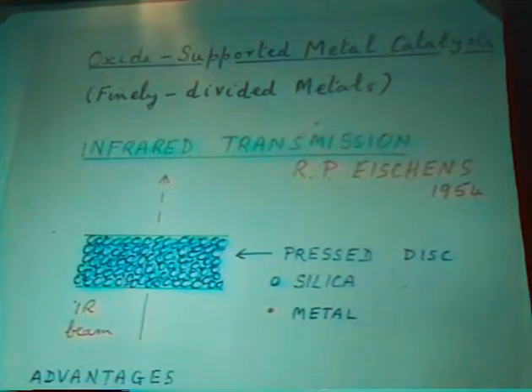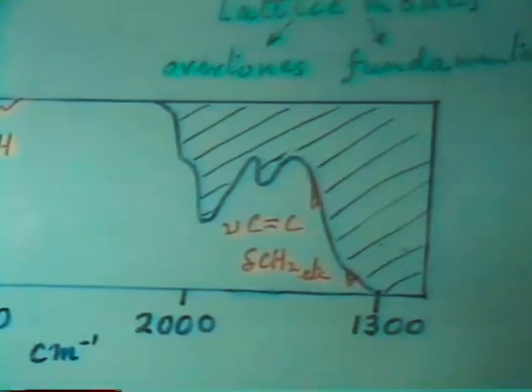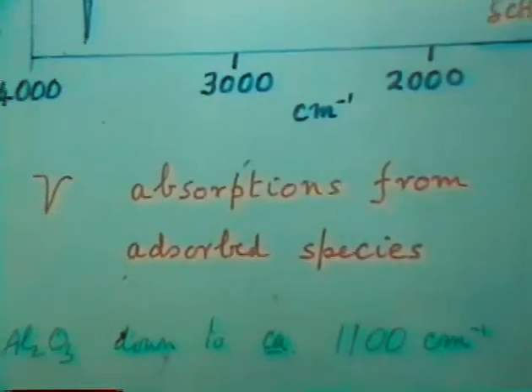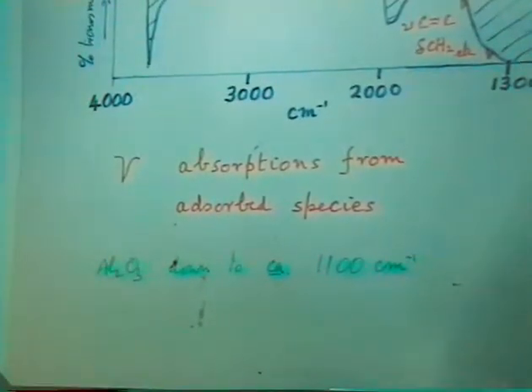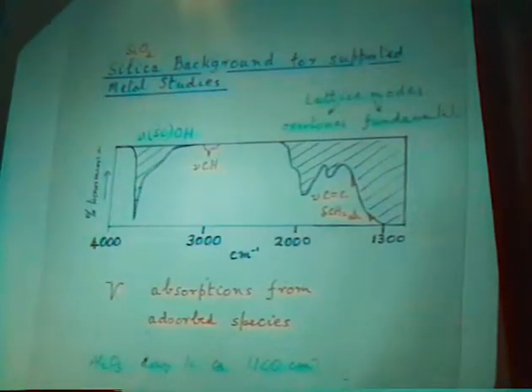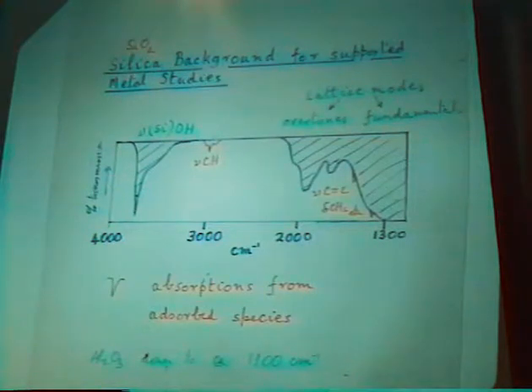We used, of course, the techniques that Bob pioneered, except we did go to the press disc technique, where you have your finely divided particles of the reduced salts into metal on the silica, all pressed together into a disc. One of the limitations of oxide-supported metals spectra is the spectrum of the oxide itself, and the hatched parts are the spectra of the silica support. Below 1300 wave numbers, this is the region of silica framework fundamentals, complete blackout. We get a number of overtones here, and then we have the chemically bound OHs on the surface of the silica after, of course, any water has been cleaned off.